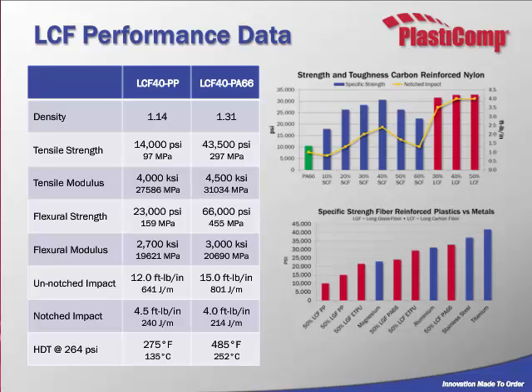Performance data here, you can see a similar story with the polymer also being a key contributor in the mechanical properties. Part of the reason you're seeing the drop in the polypropylene versus the nylon is that the polypropylene does not bond well to some of the existing carbon fibers that are available. So you're seeing a big decrease in strength characteristics, where the bonding is a little bit better between the glass and the, between the carbon and the polymer. So you get a better transfer of properties from the matrix to the fibers themselves.